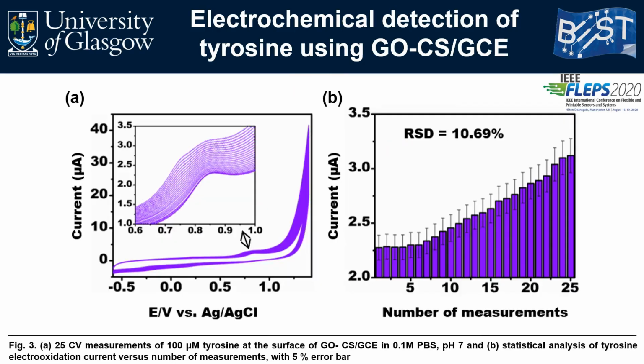The repeatability of the graphene oxide Chitosan glassy carbon electrode was also assessed by performing 25 consecutive CV scans in the presence of 100 micromolar tyrosine in 0.1 molar PBS at a scan rate of 50 millivolts per second. As can be seen from Figure 3, the sensor exhibited excellent electrooxidation response for all measurements and demonstrated good reproducibility with a relative standard deviation of 10.69%.